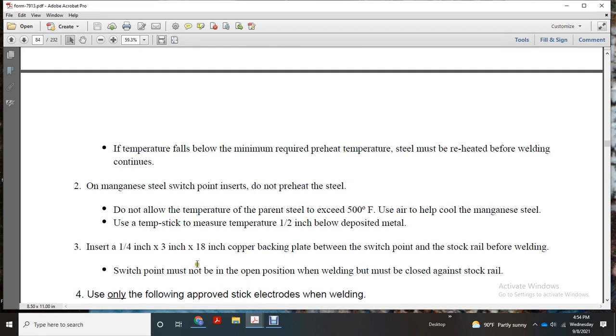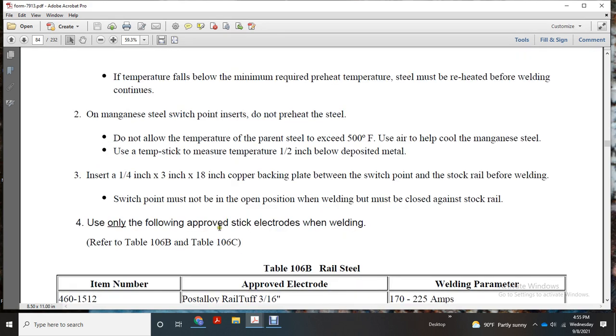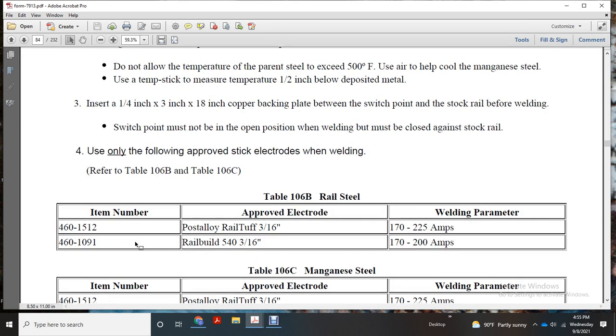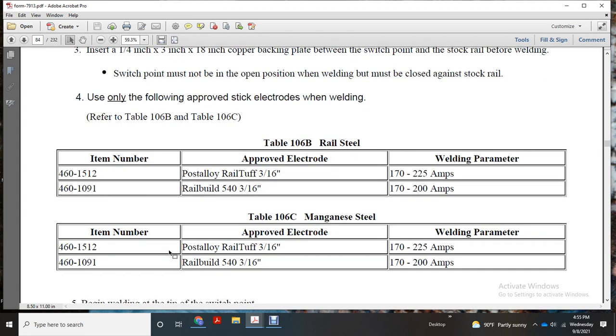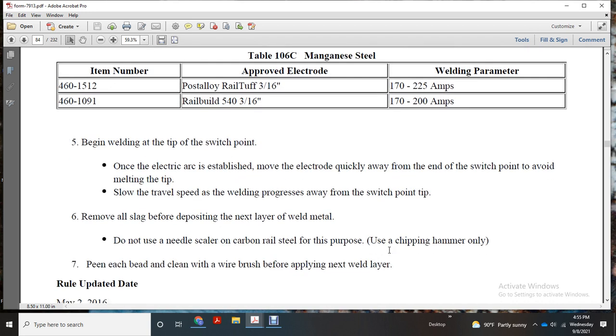Insert a 1/4 by 3 inch by 18 inch copper backing plate between the switch point and the stock rail before welding. Switch point must not be used in the opening position. Welding must be closed against stock rail. Use only approved stick electrodes when welding. Use 3/16 inch electrode at 125 amperes, and rail build 540, 3/16 inch, at 100 amperes. For manganese steel, both 3/16 inch, 125 and 200 amperes.